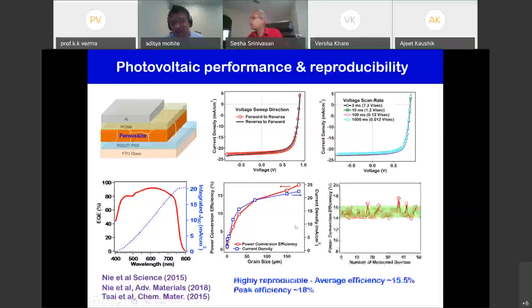Most importantly, there were also a lot of issues of reproducibility. What we showed is that these devices were very reproducible. We were able to get an average efficiency of about 15%. This is about 50 measured devices. And the peak efficiency that we reported was about 18% during that time. It was sort of a record at that time.